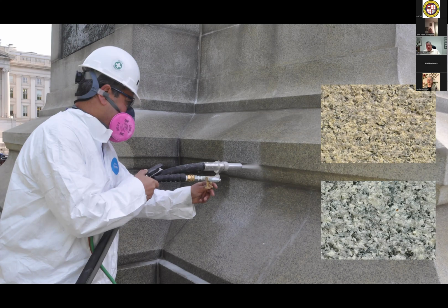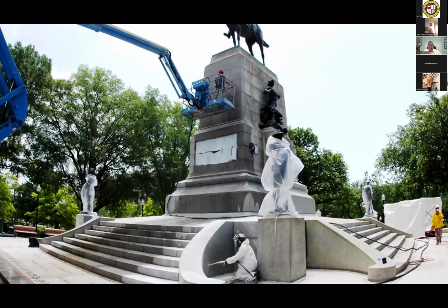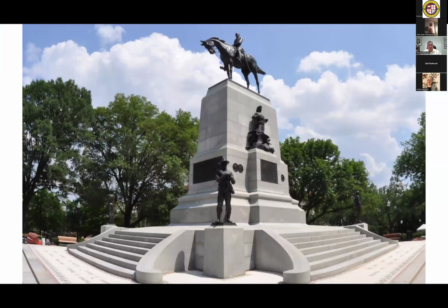This is using the Jos Rotec system, which uses microfine crushed glass media, which is like talcum powder when you feel it. And it's very low pressure. This is 25 psi, and that allows the glass to be stronger than the coating but weaker than the stone. So I remove the coating, and you can see the before and after between the two sections there. So we basically went over the whole thing with that system, cleaned the monument, protecting all the bronze elements, doing some other repairs, and here's the end product. A lot less yellow.